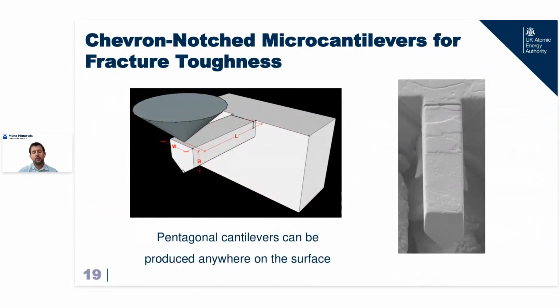And the technique that Bo came up with is this really elegant chevron notched microcantilever geometry. It's based on this pentagonal cross section milled out using the focused ion beam, so you can mill it anywhere in your surface. You're not limited to using just the edge of your specimen, so you can get much more efficient use of materials.